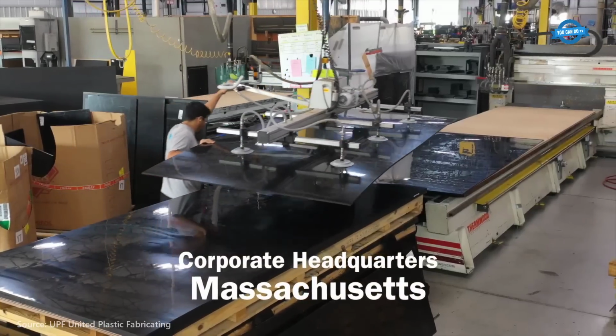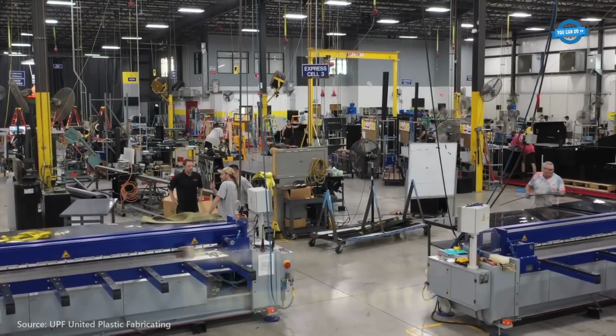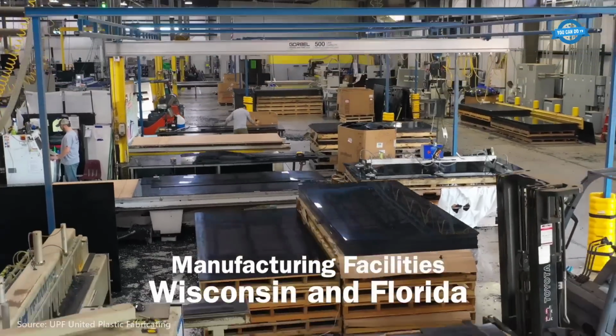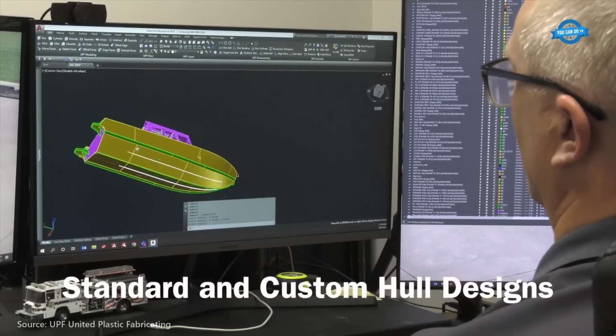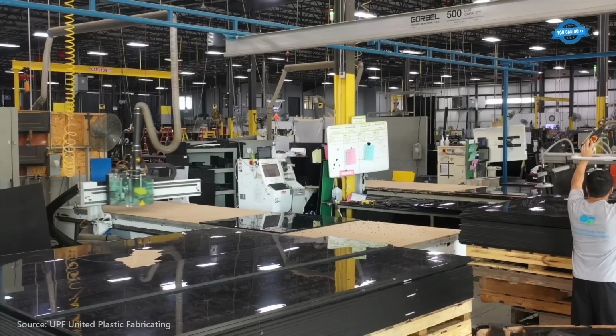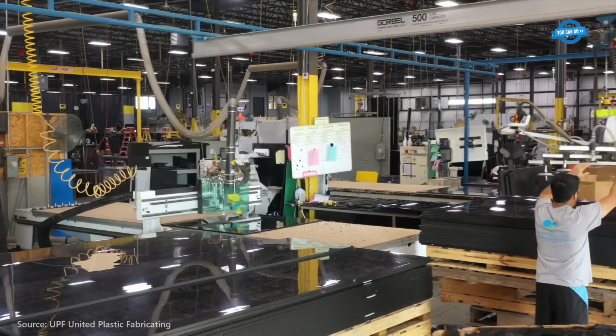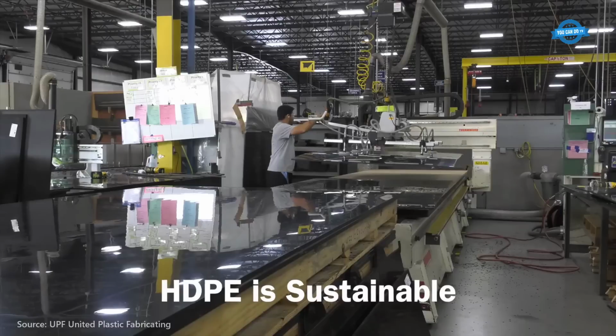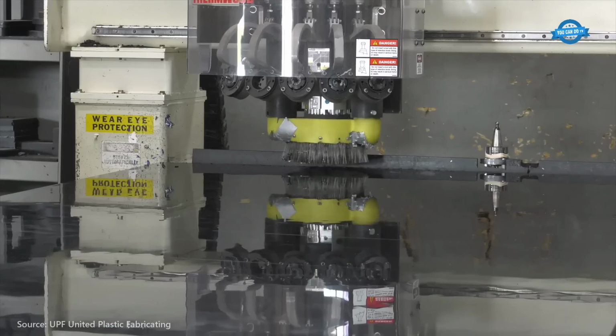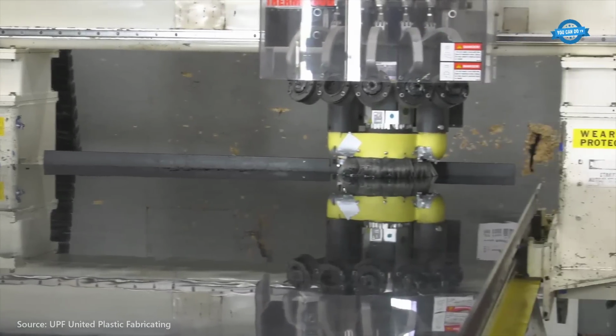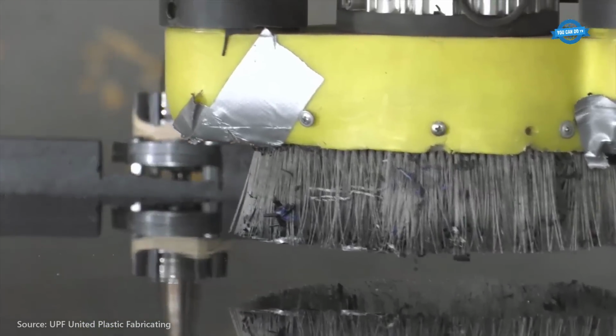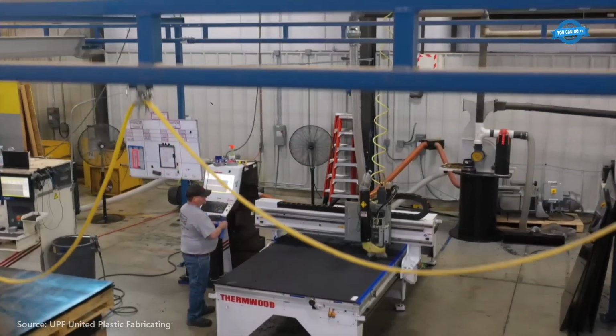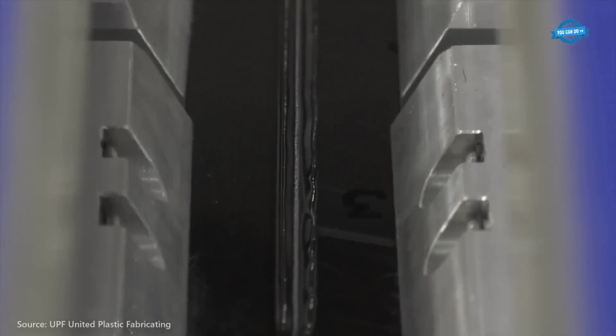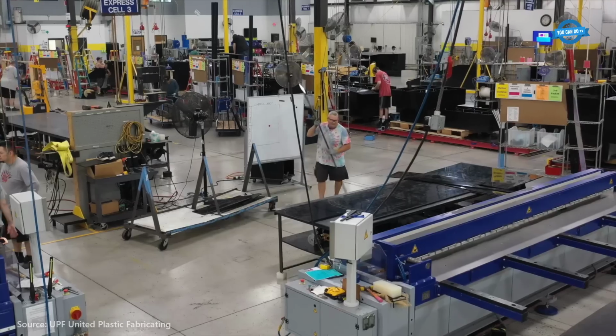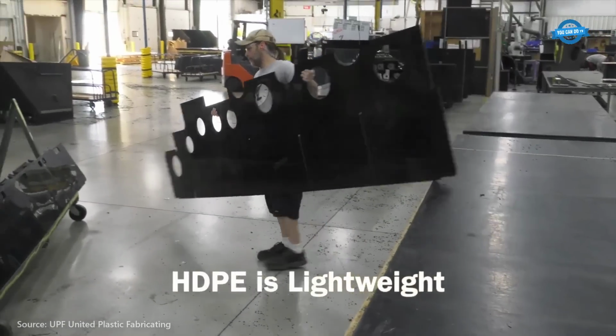The production process begins with computer-aided design (CAD), followed by CNC cutting of 12 to 25 mm thick HDPE sheets to exact dimensions. Hull components are then joined using extrusion welding and butt fusion welding, ensuring long-term seam integrity. Unlike fiberglass or aluminum, HDPE hulls are assembled without rivets or bolts, significantly reducing failure points under mechanical stress. Each hull is equipped with sealed PE buoyancy chambers and reinforced lifting eyes to support demanding operations.